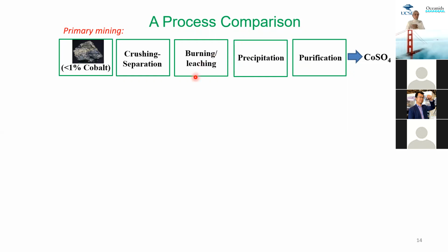And then we have to use very strong acids together with an oxidation agent, for example, sulfuric acid together with hydrogen peroxide, to dissolve them into water, into a liquid. And then we add leaching agents, complex agents and binding agents, and we add a base to precipitate them. And then we purify them by many processes. And then finally, we get this high purity so-called precursor.